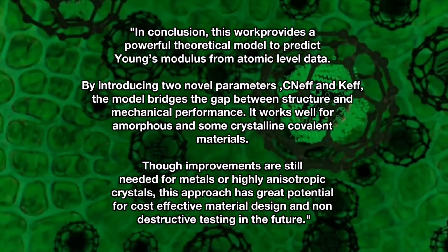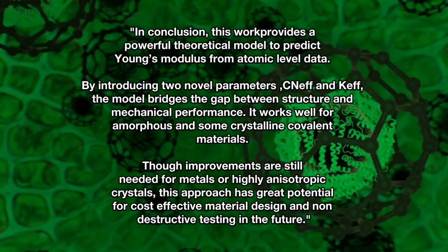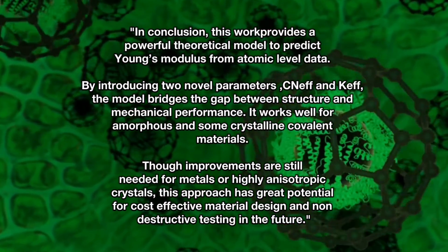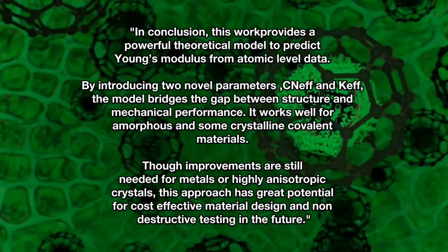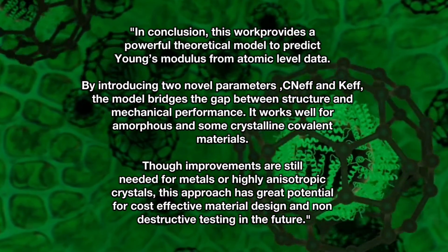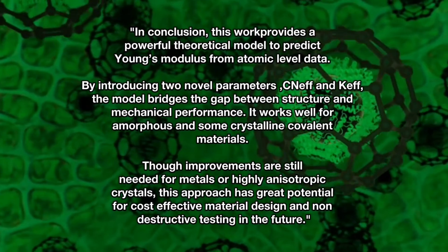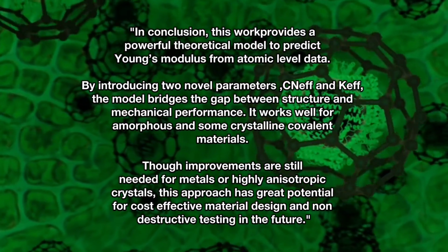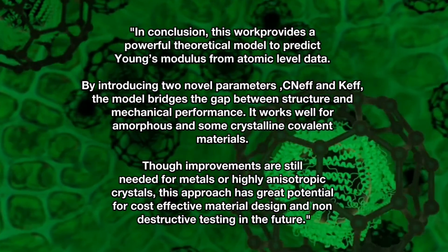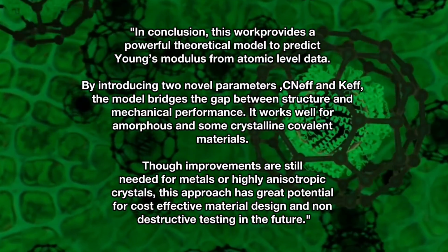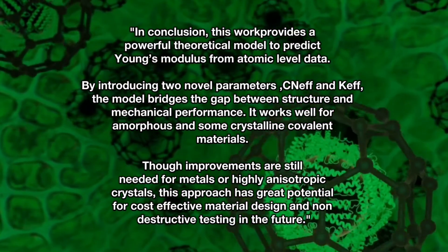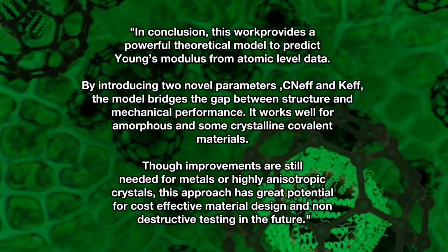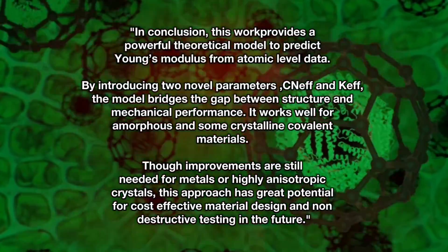In conclusion, this work provides a powerful theoretical model to predict Young's modulus from atomic-level data. By introducing two novel parameters, the model bridges the gap between structure and mechanical performance. It works well for amorphous and some crystalline covalent materials, though improvements are still needed for metals or highly anisotropic crystals. This approach has great potential for cost-effective material design and non-destructive testing in the future.